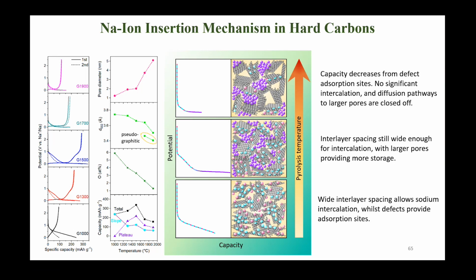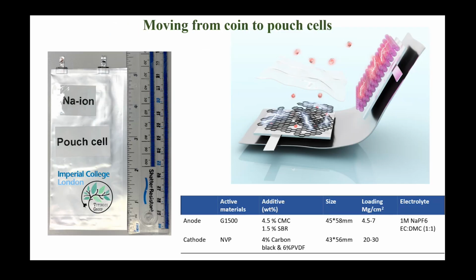You can have very big pores, but if your interlayer spacing and graphitization is too high, sodium cannot go in and access this pore. So ideally, to make the ideal carbon, you need a combination of heteroatoms, interlayer spacing within a very sweet spot, and then pores where sodium goes and plays, and metallic sodium.